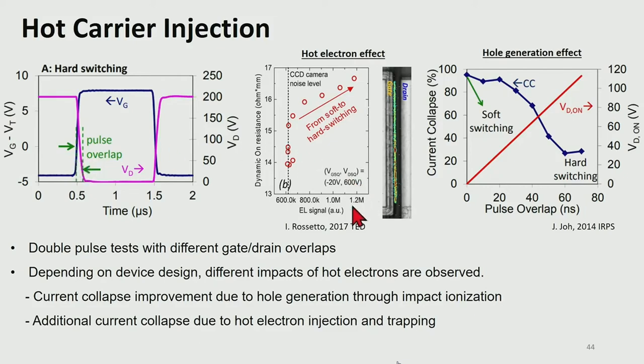The study shown in the center figure studied the impact of this overlap time on device behavior. If you see this center figure, with increasing overlap time, the EL signal coming out of the device increases, because with a longer overlap time, the number of hot carriers increases. At the same time, the dynamic RDS,on performance is degraded because of the hot carrier injection mechanism.